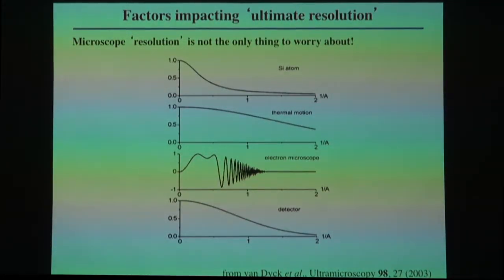Okay, so I'm not trying to de-advertise the benefits of aberration correction, but I think you need to be going in with your eyes open, because microscope resolution is not the only thing to worry about. For example, a silicon atom, as you go out to higher and higher scattering angles, does not scatter so much. You also have a problem that when you go out to higher and higher scattering angles, you have to take account of the fact that the atoms are vibrating. They're not really in one position.